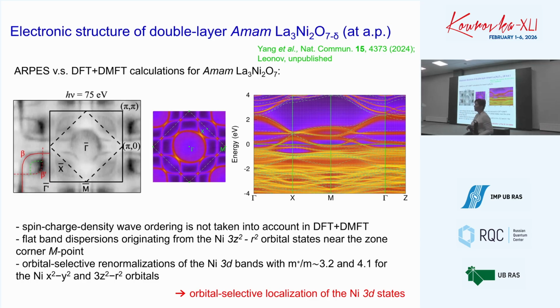How does the TC of the thin film samples that show superconductivity at ambient pressure depend on the film thickness? I'm talking about the first part. So I'm not sure that there is an increase of TC. Of course, there is a critical thickness of 4 or 5 nanometers, and then TC is roughly similar, like 15K. And I've seen people go to 25 nanometers, and it was nearly the same.